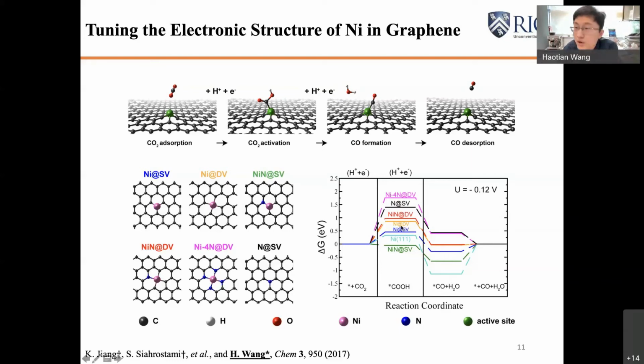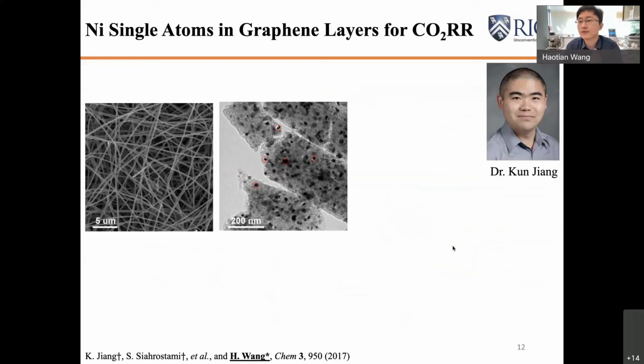But if you look at these nickel single atomic sites, even though the first CO2 activation barrier is slightly higher than nickel metal, which can be offset by applying more negative overpotentials, the CO desorption becomes much better. So that gives us great confidence that this type of nickel single atomic site might be a very promising site for us to reduce CO2 to CO. So at that time, we were thinking about how to controllably synthesize the nickel single atoms. But at that time, we didn't have the experience to make that happen. So what we did was mix all the precursors together and use an electrospinning technology to spin out carbon nanofibers and do the annealing process.